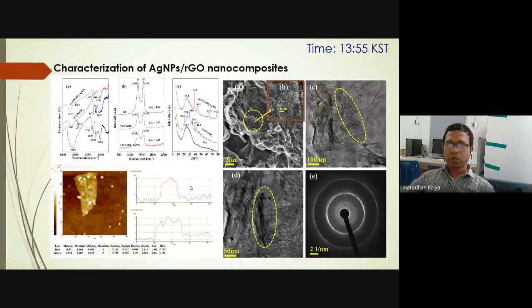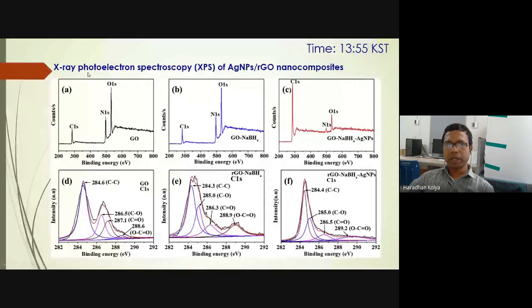And this is one of the most efficient techniques for characterization of the nanoparticles, that is X-ray photoelectron spectroscopy, XPS. According to this XPS, as I already mentioned, graphene oxide has a higher number of oxygens, but in reduced graphene oxide there will be a lower number of oxygens, meaning a low intensity of the oxygen value. And if you see the percentage of carbon, it will be higher, and it is even higher in the reduced graphene oxide with these nanoparticles. And these are the deconvoluted image structures, and you can get an idea about the binding energy changes, and from these changes you can predict the binding energy difference.